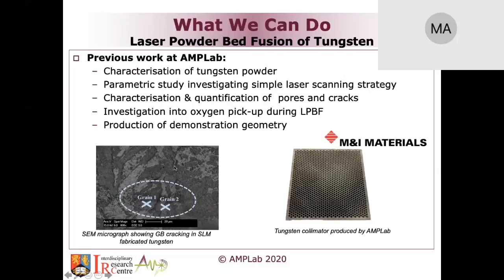And you're able to get, as you can see in that micrograph, in general, it is dense. You don't see many pores, but you obviously can see cracks. Between grain 1 and grain 2, there's an obvious crack here. There is an obvious crack there. So the material is cracked.